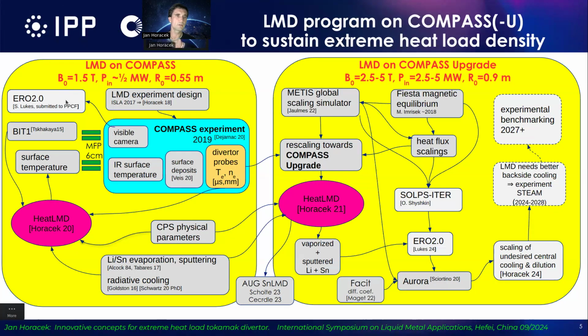And then also the output of the visible camera was compared with the ERO2 simulation, just now submitted to Plasma Physics and Controlled Fusion. And then, because this comparison was relatively successful, we used the same code using the same data from divertor probes with very high time and space resolution, and rescaled them towards COMPASS Upgrade, which has much higher power, low density, but we know how, thanks to the scalings. And then it yields, using the same code, the amount of vaporized and sputtered lithium and tin particles. And this then goes into the main plasma, up to the separatrix, and then using the SOLPS simulations and the ERO code, it yields input into Aurora, which calculates using fixed diffusion coefficients the amount of radiation in the plasma. So how much it cools down the main plasma and how much it dilutes it. And this I'm going to show you in a moment.